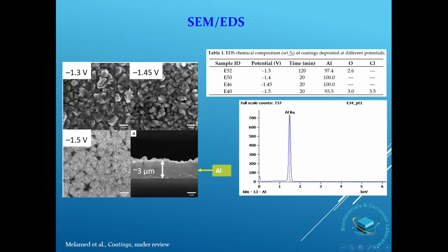The figure on the left side shows both top view A to C and cross-section D of aluminum coatings deposited under different potentials. Fairly dense and uniform crystalline coatings are evident. The grain size changes from several hundreds of nanometers at minus 1.3 volts down to several dozens of nanometers at minus 1.5 volts. Image analysis of the same cross-section images gave a deposition rate range between 11 and 734 nanometers per minute. Basically, EDS analysis showed that we get in some of the cases pure aluminum.